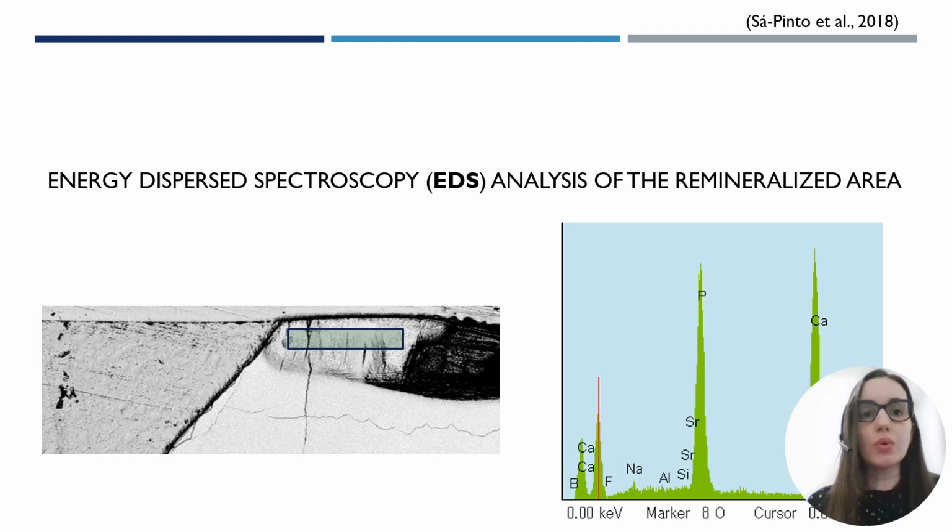So we checked using EDS device the presence of phosphate and calcium, which means remineralization in this area. So we conclude that the bioactive composite resin can prevent demineralization near the restoration and also can promote remineralization of the remaining dental structure.